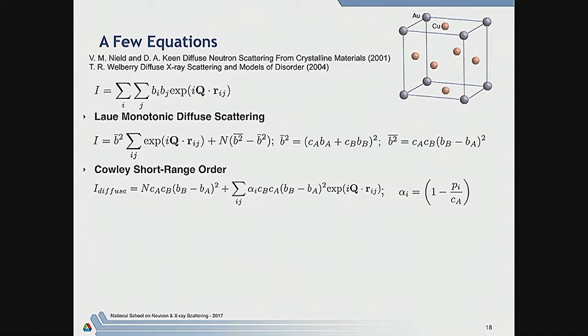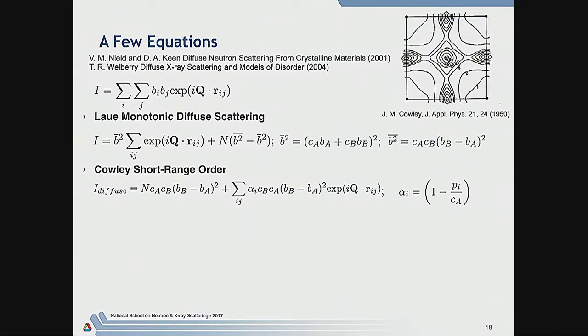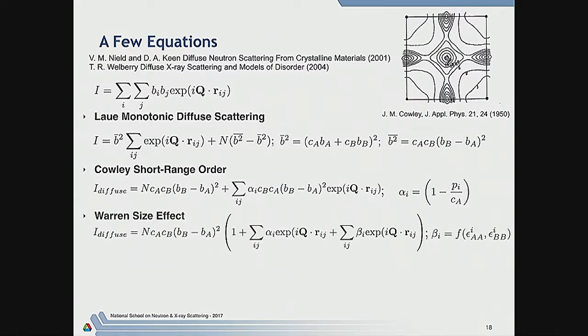But if it's not zero, then this basically is a way of modeling the probabilities that you have a tendency to have clustering. You know, if you have a B, then is there more likely to be a B next to it or atom A? And from that, you're able to actually produce a model of the diffuse scattering. And here's the tendency for these extra peaks to form in diffuse scattering. Eventually, these peaks will actually become the extra peaks that appear in the FCC structure. Okay, so diffuse scattering here is a precursor of an order-disorder transition.